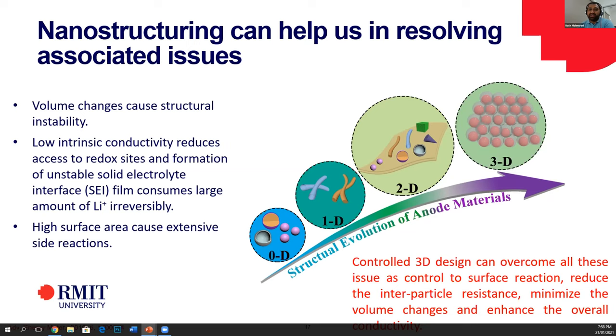And then we moved towards 2D and their composites that give us a lot of benefits: higher conductivity, higher storage, and more stability. But still, the active materials on 2D sheets or carbon sheets get deteriorated after some time. So we need 3D designs which connect individual particles. They protect the surface of individual particles, and then they also cover the overall structure in one conductive matrix that connects directly to the current collector. So overall, we can confine everything. We prevent side reactions. We control the solid electrolyte interface film. We have easy penetration of electrolyte.